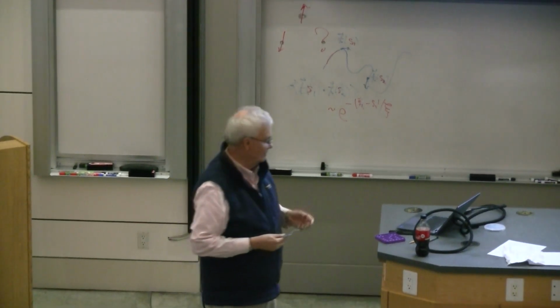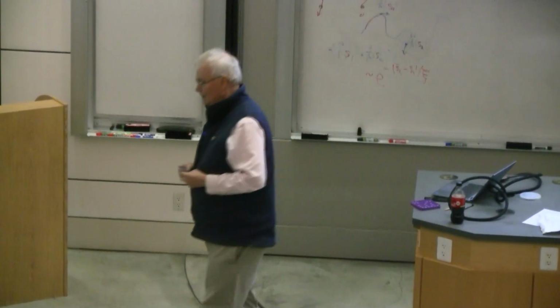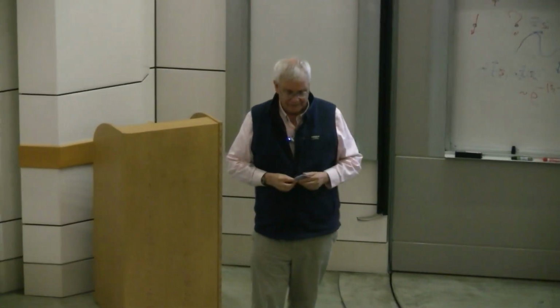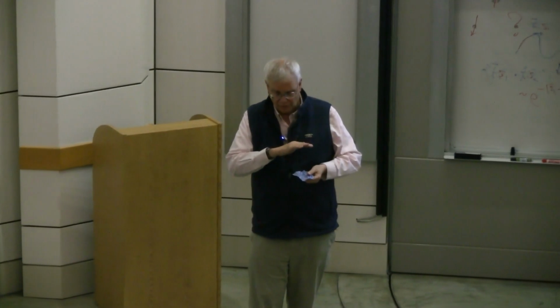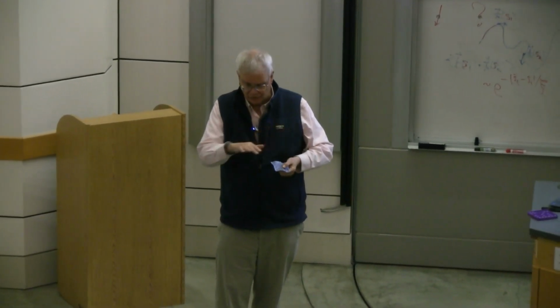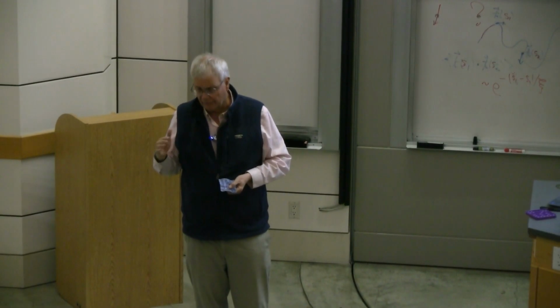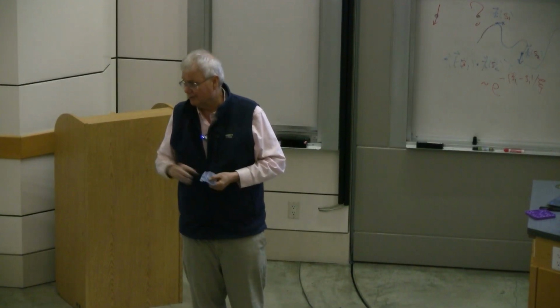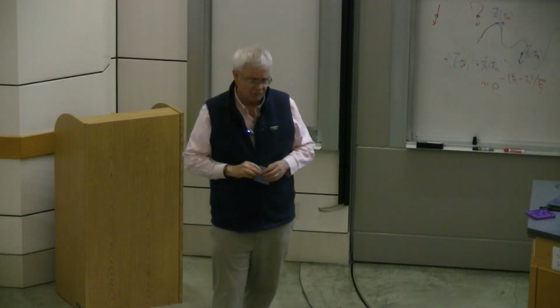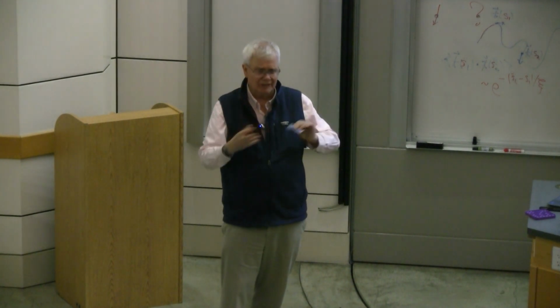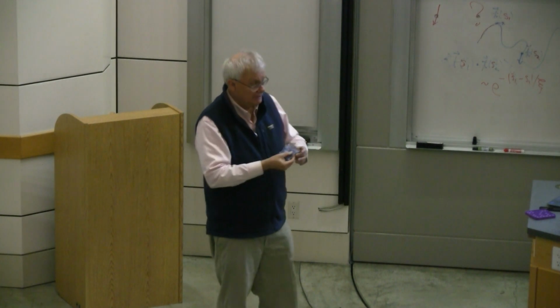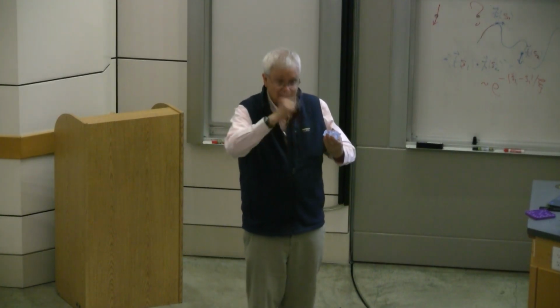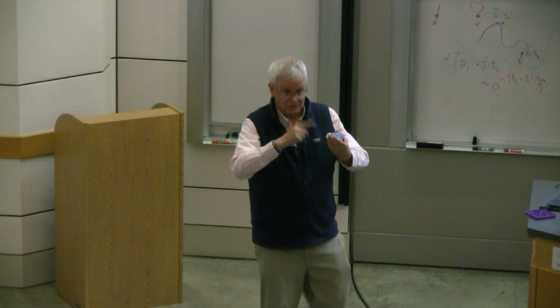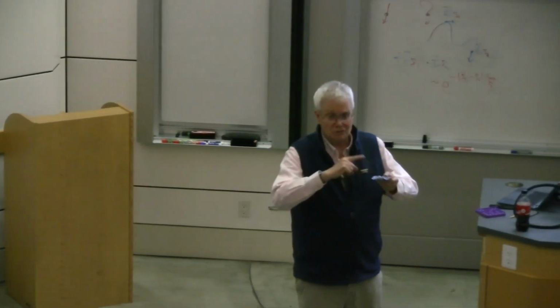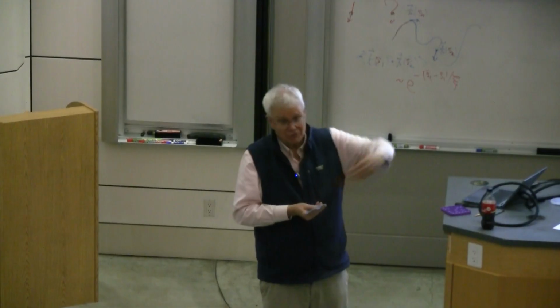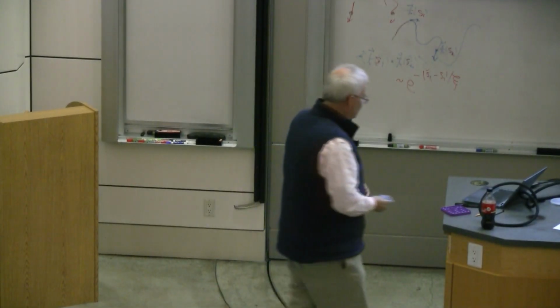And again, the logarithm? It's a quenched random average where you have an average over the disorder, and probably can be related to the derivative of the logarithm of the partition function in the usual way. So that's how the calculation was done. It's summing a bunch of Feynman diagrams, and it's predicted that the standard deviation also grows linearly. So the bending rigidity is growing linearly, and the standard deviation is growing linearly.